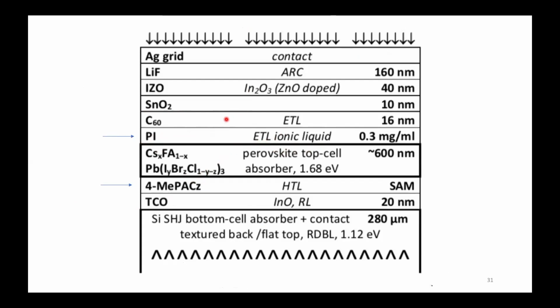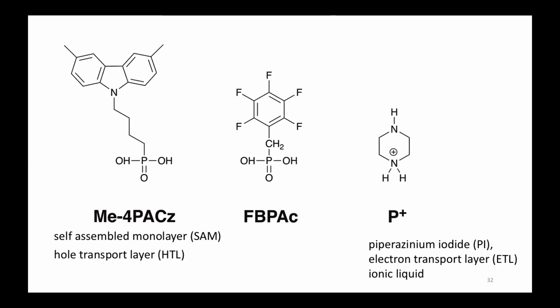And there we have C60 on top of it, then some tin oxide, some other layers, some anti-reflective materials. On the bottom, there we have this self-assembled monolayer of this carbazole molecule on top of a very, very thin layer of transparent conductive oxide, indium oxide in this case. So you see, we have a multi-layered stack, very, very thin layers, less than 100 nanometers. It's nanotechnology. And we even have a self-assembled monolayer of this molecule.